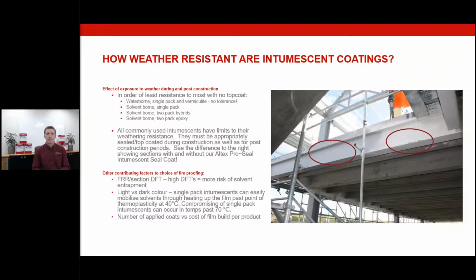Solvent-borne single pack are much better, but still have their limitations. Solvent-borne, both two-pack hybrids and two-pack epoxy, are the most resilient of those groupings of intumescents. You'll commonly see on data sheets weather resistant to 3 months. That's assuming it's a rain cycle and it sits on the steel for maybe a couple of hours and then dries off. Not your atypical New Zealand weather where you get torrential rain for a week and everything's sitting dripping wet for quite a number of days.